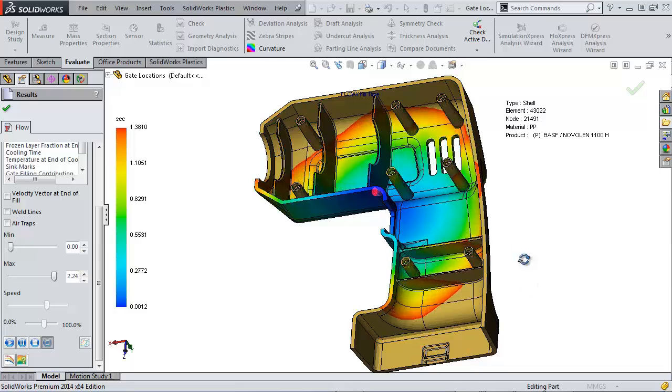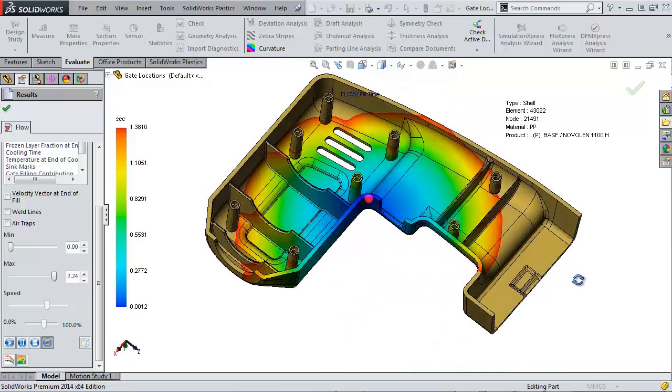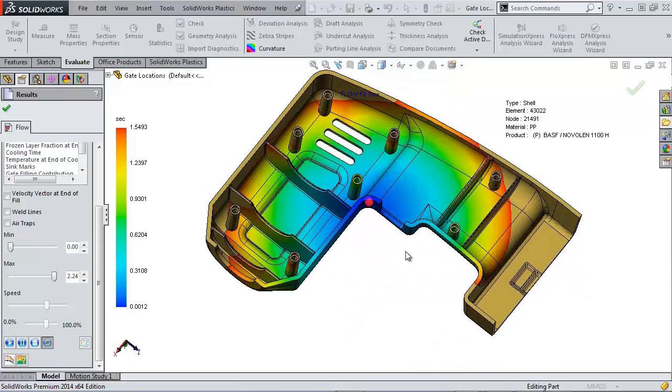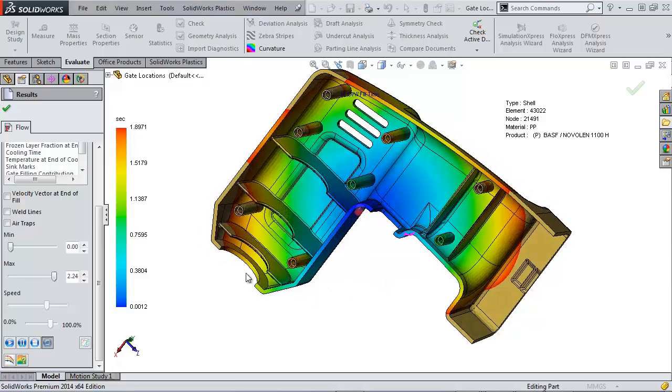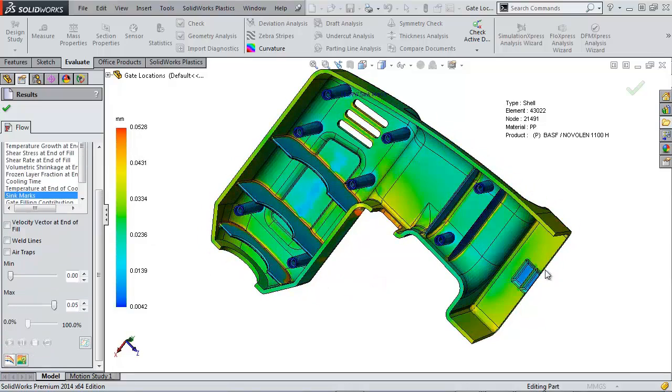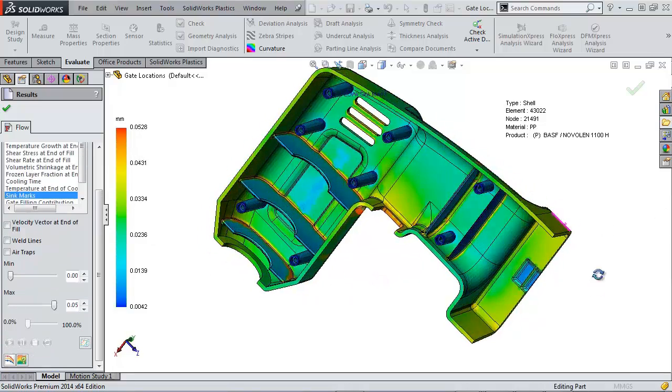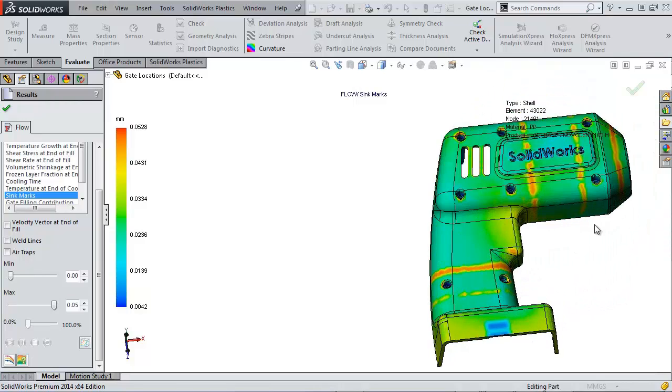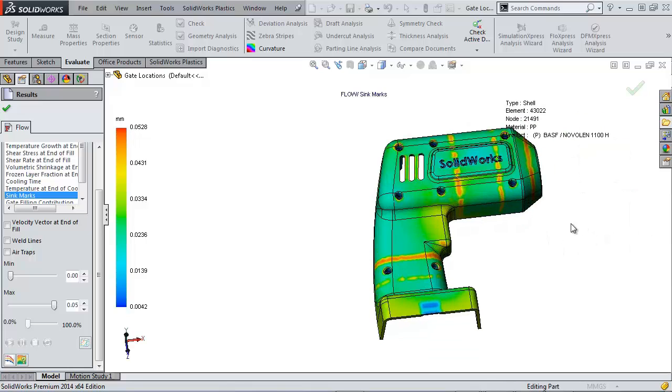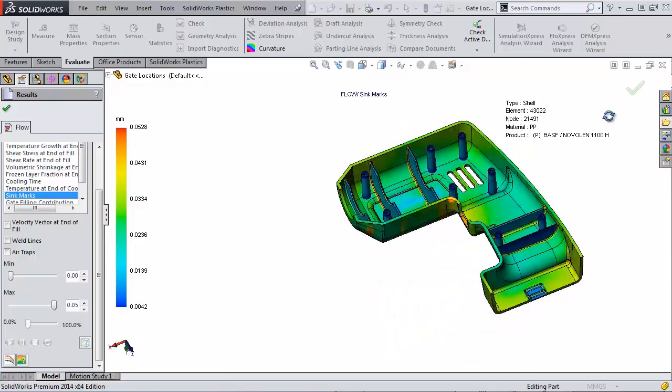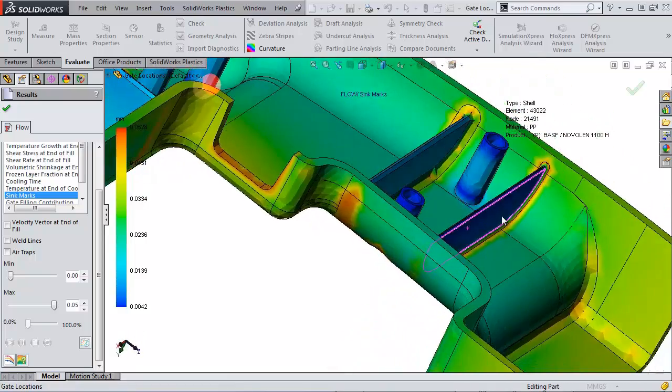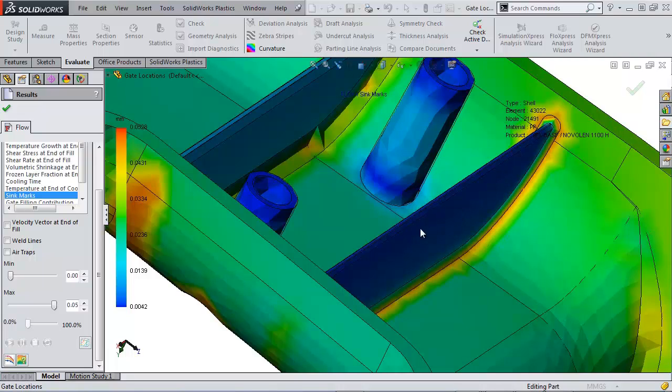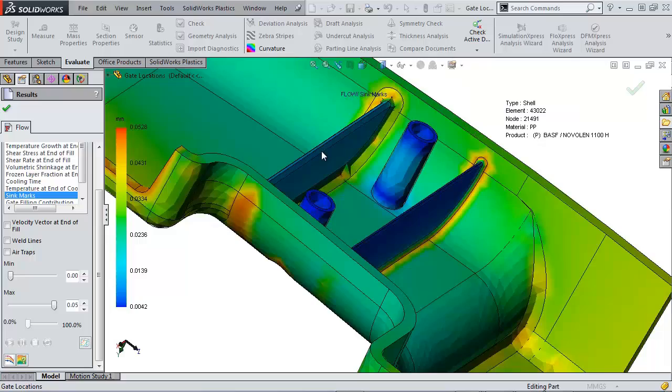But I have a lot of ribs in this design, and I'm curious if that's going to be pulling in any of the materials on my shell. So if we look at our sink marks, we can see the effects of all of our ribs pulling in our part. So again, this is added material on the back, it's cooling at a different rate. And we can see if we flip this over, that our rib here is about 70% thinner than this rib over here.